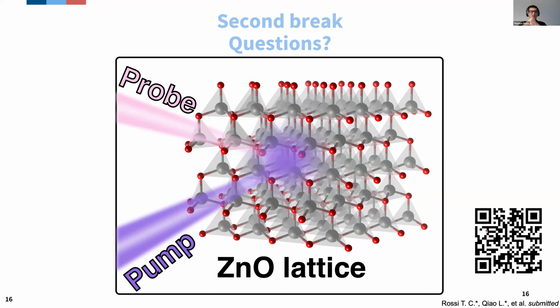However, as you go to shallower and shallower edges, the radius of your exciton starts to become larger and larger. And we expect that this now starts to become more affected by all this incoherent thermal motion that you have in your system. So this approach should be less and less valid. And in fact, we did observe that at the zinc L3 edge, this splitting into two contributions was not as good as what we observed at the zinc K edge. Basically, I hope this addresses the question. So no shift when we remove thermal signals. It's a pure subtraction. Okay. Yeah, thanks.